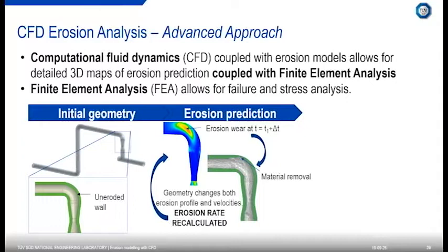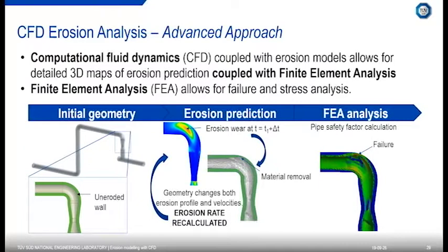And so what that's then doing is changing the geometry, which will change the velocities. It'll then change the impact angles and the particle velocities at the wall, and it'll alter the erosion rate. And then we can perform our finite element analysis if we so desire. For example, in this case, if the pipe is under pressure, it may fail for a particular wall thickness, and we can determine that.